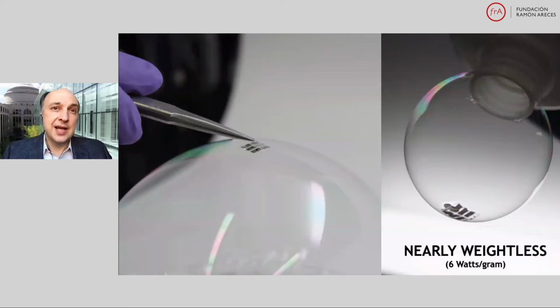And this is an example of an extremely light cell, one that was made on a 1 micron thick polymer substrate. We grew the polymer substrate first, and then we grew our solar cell on top of that. The entire structure is about 2.5 microns thick, if you include the encapsulation layer on top. And it's light enough that you can rest it on a soap bubble. The soap bubble, hence, demonstrates to you just the power of this technology. This is 6 watts per gram of a solar cell, 6 kilowatts per kilogram. And in this particular version, we are not even using the most efficient solar cells we have.